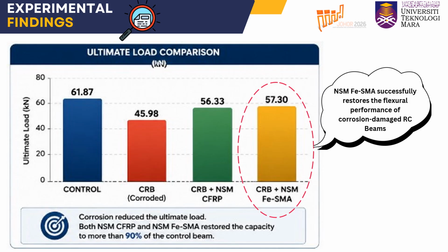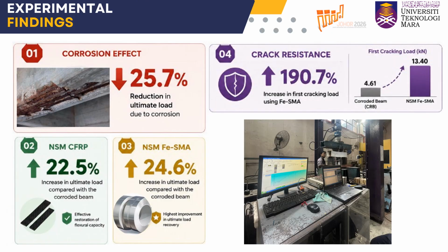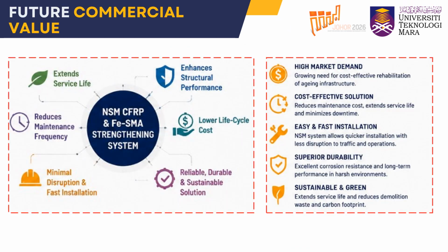Half-cell potential measurement confirms successful corrosion induction. The findings show corrosion reduced the ultimate load. After strengthening, both NSM CFRP and NSM Fe-SMA restore more than 90% of the original beam, with Fe-SMA achieving the highest performance. Corrosion caused a 25.7% reduction in load capacity. NSM CFRP improved the ultimate load by 22.5%, while NSM Fe-SMA achieved an improvement of 24.6%.